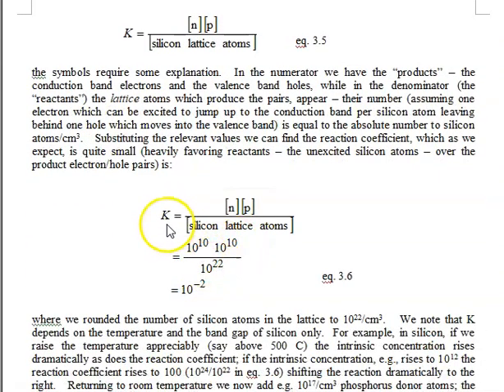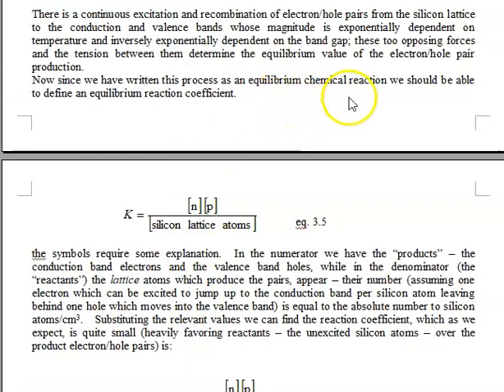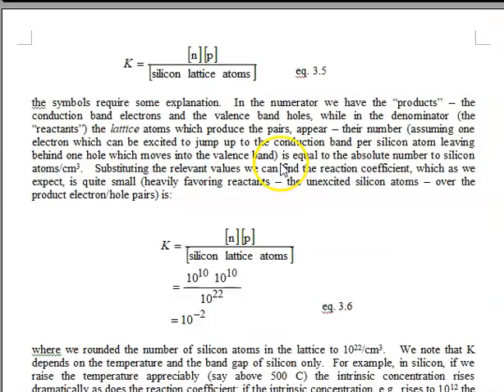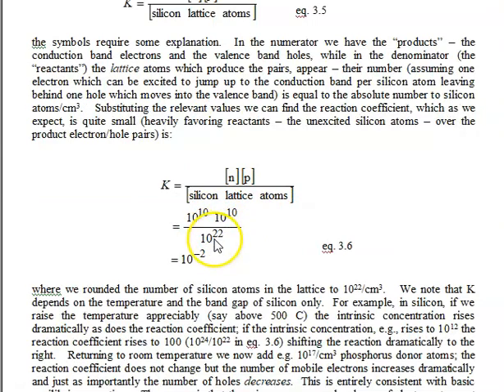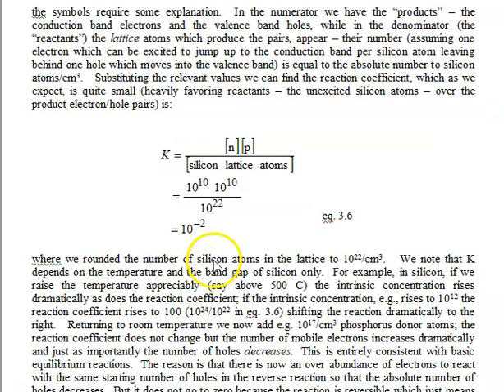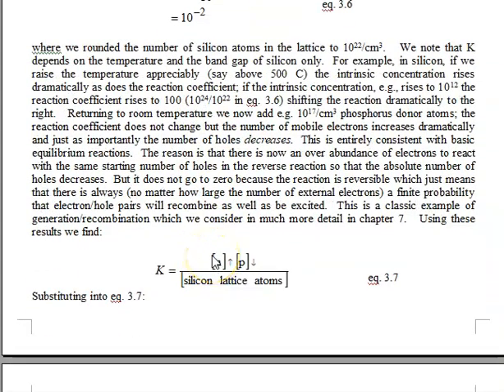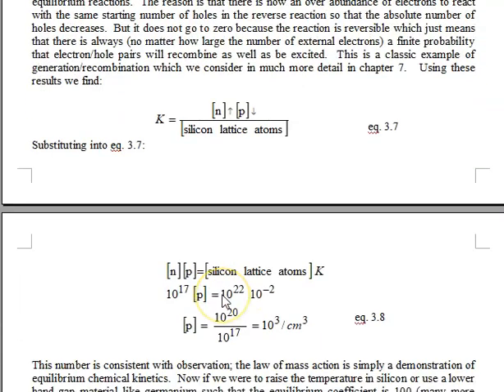So we just put that in, and we find that the equilibrium reaction coefficient is equal to 10 to the 20th divided by 10 to the 22, or 10 to the minus 2. Now, here's the trick. We're going to dope our silicon lattice with lots and lots of electrons. We put in a relatively large dose of phosphorus. It ionizes, and I believe I said that this was 10 to the 17th. So N now has jumped up from 10 to the 10th to 10 to the 17th, and I want to find out what the P is. Well, the reaction coefficient hasn't changed. It's still 10 to the minus 2.